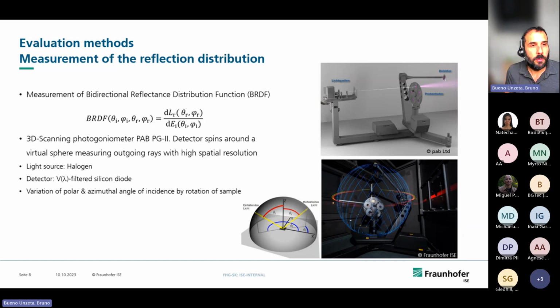The photogoniometer, or one of the photogoniometers we have at Fraunhofer, is a three-dimensional scanning photogoniometer from the manufacturer PAB. And for this device, we illuminate a sample with a light source. In our case, it's a halogen lamp. And then we have a robotic arm with a V lambda silicon diode detector, which moves around the sample. So it moves actually through a virtual sphere of 1 meter radius, and it measures the light intensity at different positions around the sample. So if it's measuring in front of the sample with respect to the light source, it would be measuring a scattered reflection. If it's measuring behind the sample, it is measuring a scattered